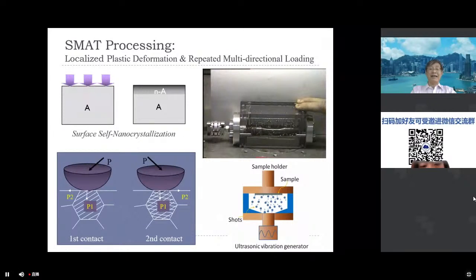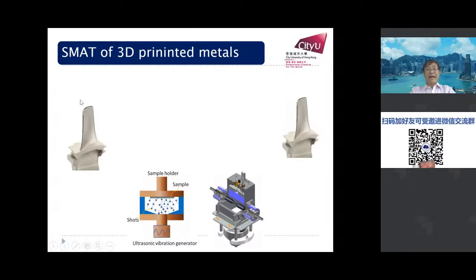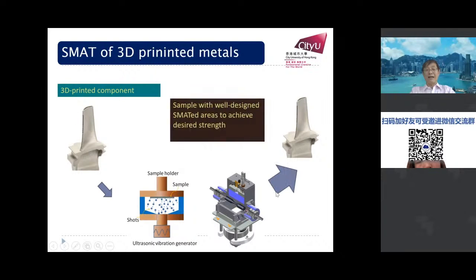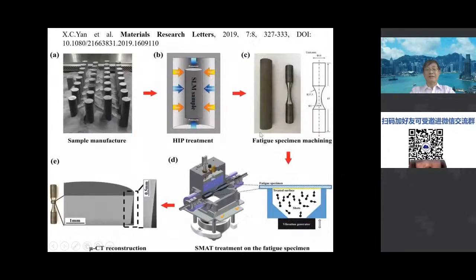However, 3D printing metallic structure has a problem with fatigue. As you know, all these mechanical components need to have a high fatigue resistance. So how to improve the fatigue resistance of 3D printing metallic structure? So the surface mechanical attrition treatment is a very good example. So the basic idea is to take the 3D printed component and use the SMAT for the treatment and then enhance the fatigue strength. So to test this, because the surface mechanical treatment, is it possible to enhance a very large sample? So fatigue strength, that is questionable.